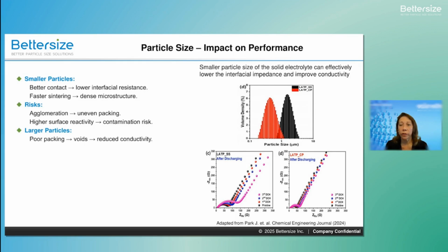But there's a trade-off. Too fine a particle can agglomerate, and this can cause uneven packing and contamination risks. Overall, the smaller particles improve ionic conductivity, but may increase surface reactivity and instabilities.